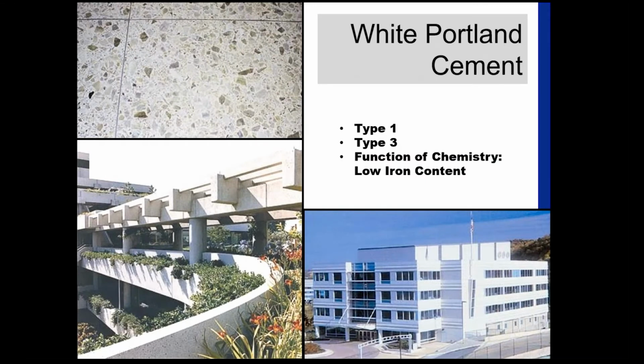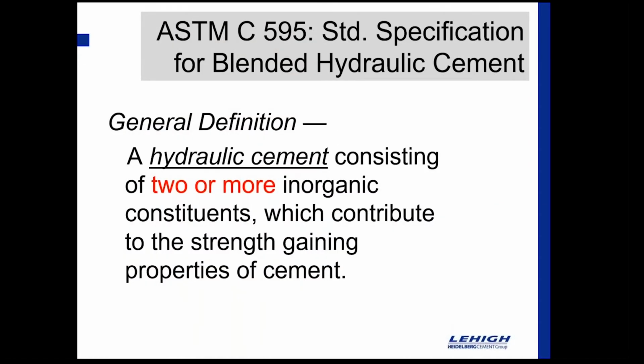Just real quick while we're in the neighborhood, thought I would just mention white Portland cement. And you can get a white Portland cement in either a type 1 or a type 3. And the whiteness is a function of chemistry primarily, very, very low iron content. It's a special process, a special kiln. Not every cement plant can do that. So it tends to be a little more expensive because it's a matter of scale and a little harder to get. So it's a supply and demand issue. But again, just a function of the iron content, and we'll talk about why that would be the case here in just a bit.